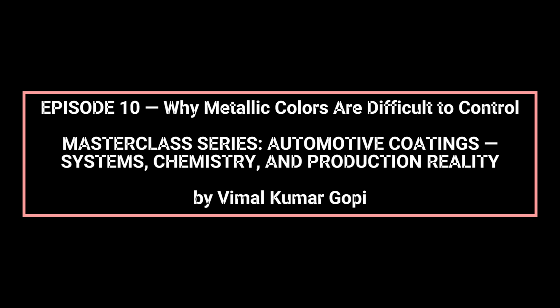The difference between laboratory panels and full vehicle bodies further exposes metallic instability. Flat panels provide uniform airflow, orientation, and thermal mass, enabling ideal flake alignment. Vehicle bodies introduce curvature, vertical surfaces, edges, and cavities, all of which disrupt solvent evaporation and flake mobility. A metallic base coat that appears stable in the lab may fail OEM appearance audits on full bodies.